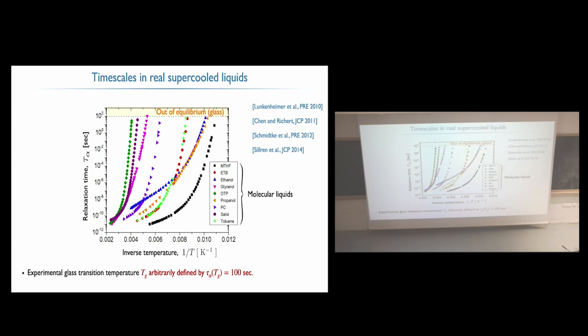And what you see is really this dramatic shoot up of the relaxation time. It increases by 12, 13 orders of magnitude when you change the temperature just a very little. Okay, so the structure doesn't change, dynamics is completely different. And again, here in experiments, we say that we arbitrarily define on our human timescales that the glass transition is when this time is 100 seconds. It's just too long, you don't want to wait. Okay?